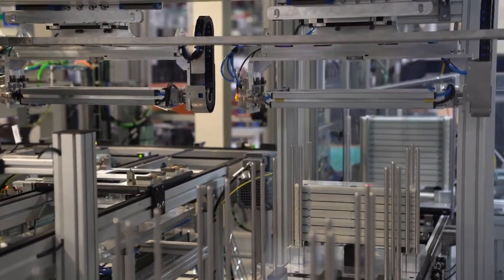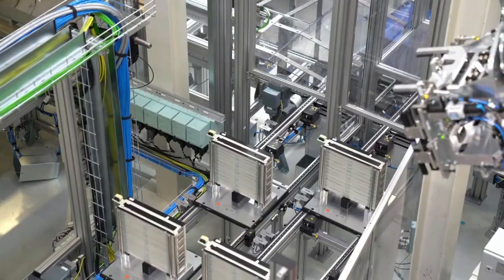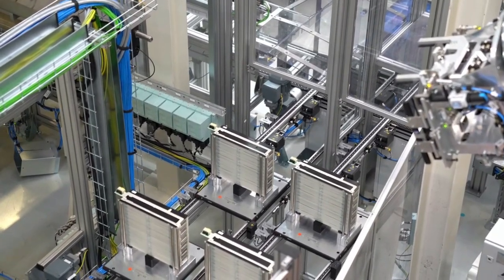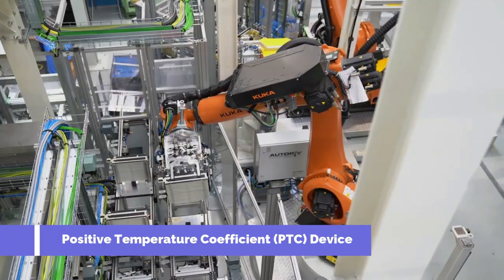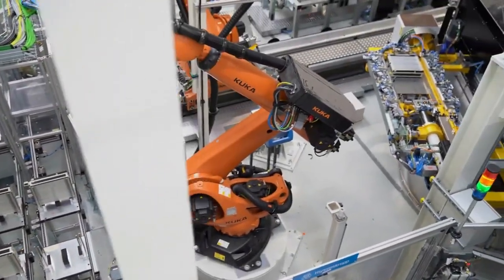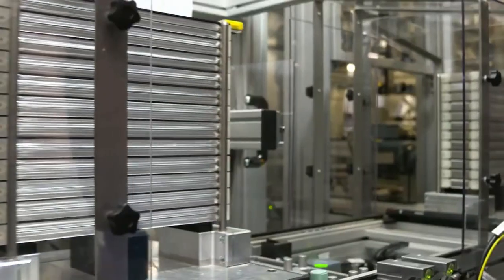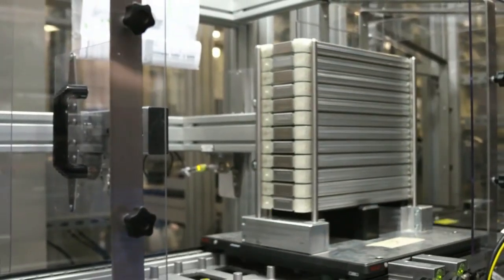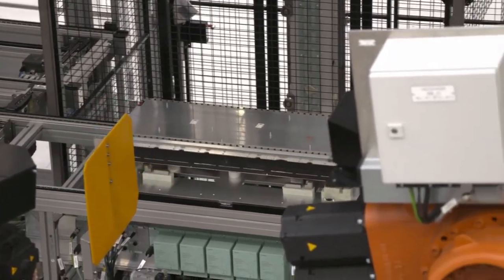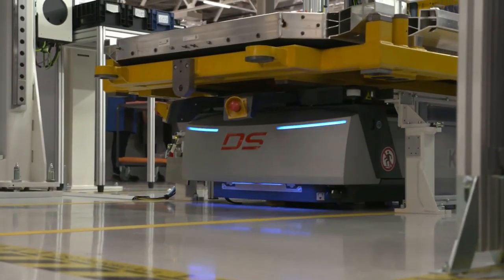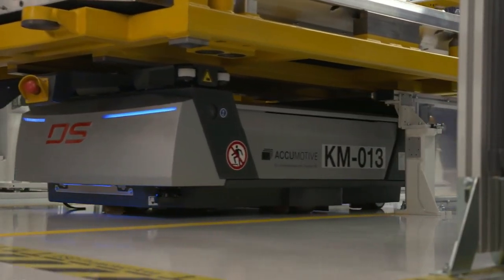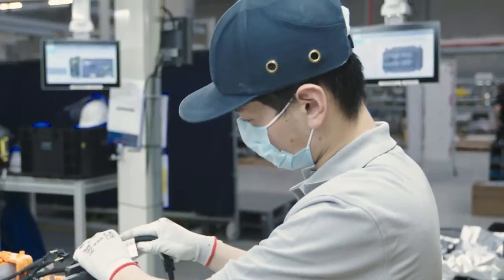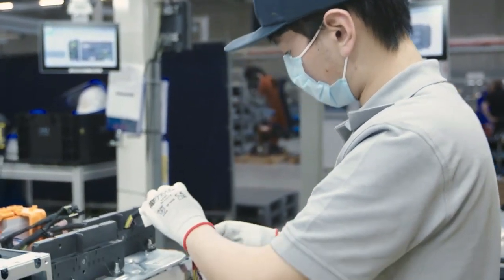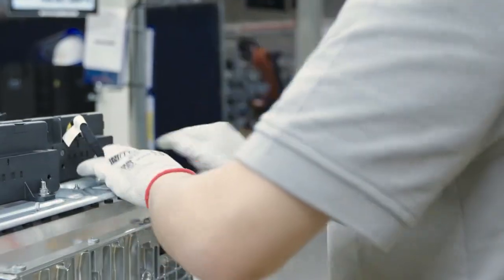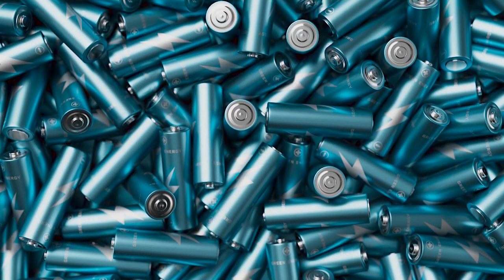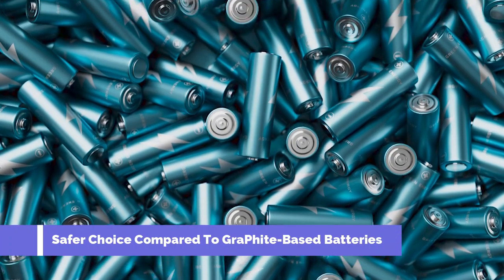In terms of safety, silicon anode batteries have several safety features. They include a positive temperature coefficient, or PTC device, to protect against high current surges, a circuit interrupter to prevent excessive charging voltage, a safety vent to release gas during rapid pressure increase, and an external electronic protection circuit that opens a switch at 4.30 volts. Additionally, a fuse cuts off the current flow when the external temperature reaches 90 degrees Celsius. These features make silicon anode batteries a safer choice compared to graphite-based batteries.